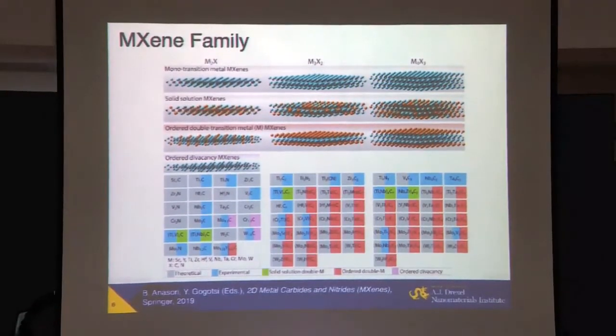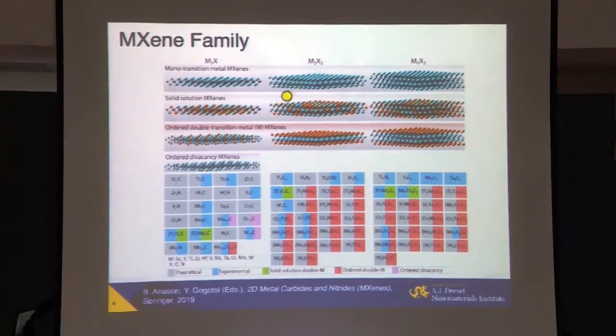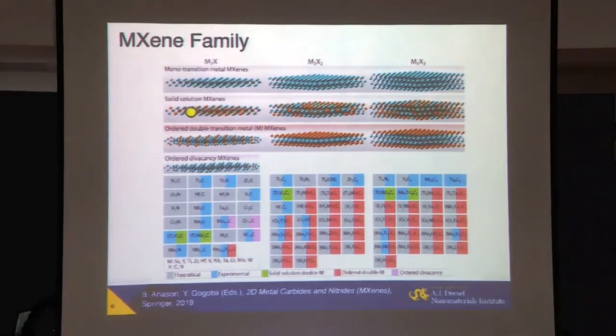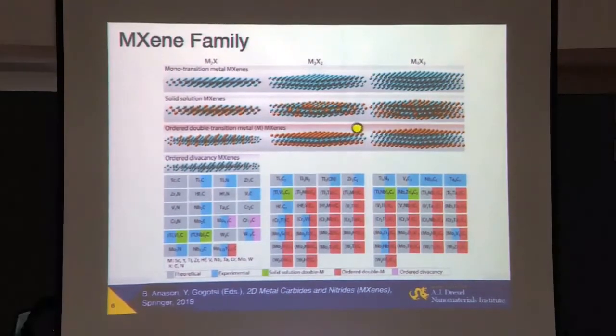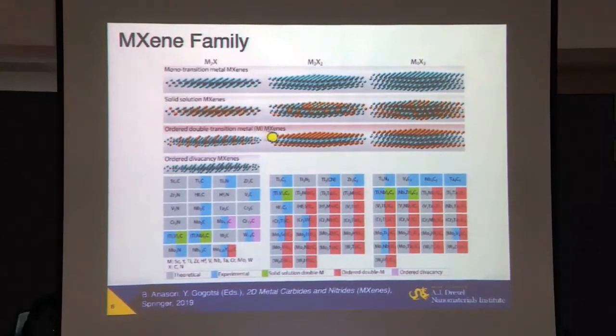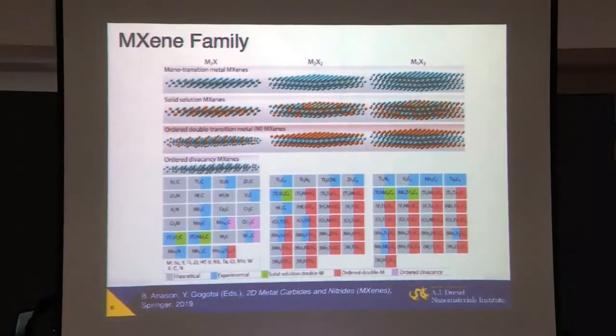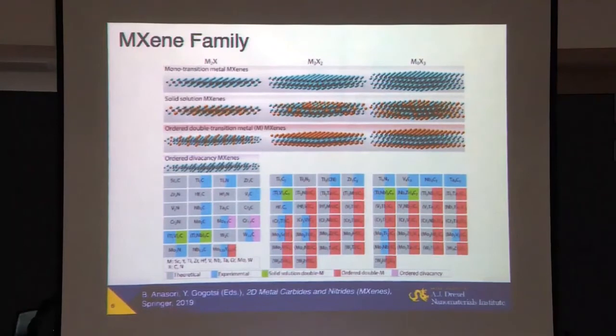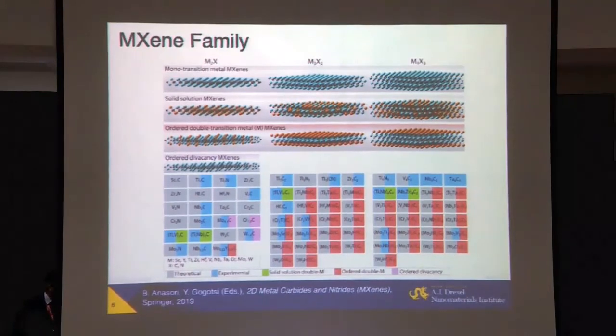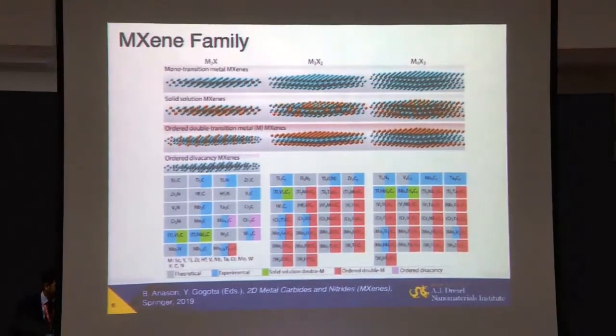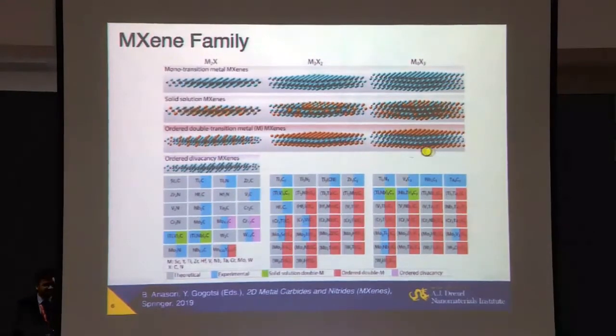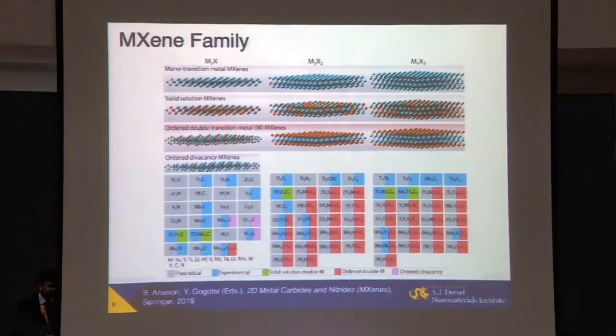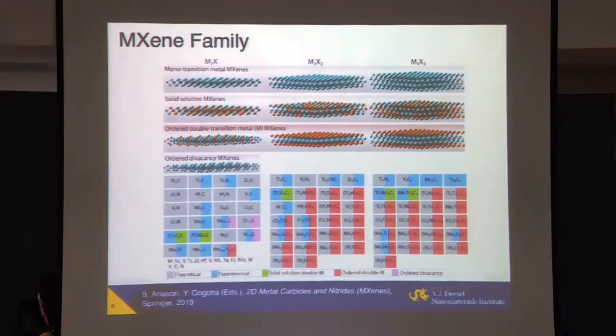Just in my lab, I now study about 25 different solid solutions here. They also can be on the X side. We call them carbonitrides, carbon and nitrogen. But moreover, we can take atomistic design to the next level and make atomic sandwiches, where one element, like molybdenum, is on the surface and titanium is in the middle. So the surface element will largely determine the surface chemistry of the material, its catalytic properties, energy storage ability, sorption, and others, while the metal in the middle, which is a monolayer or double layer, will largely determine the electronic properties of this material. And this is not all.